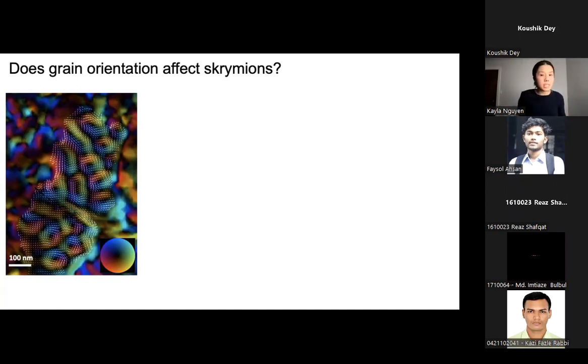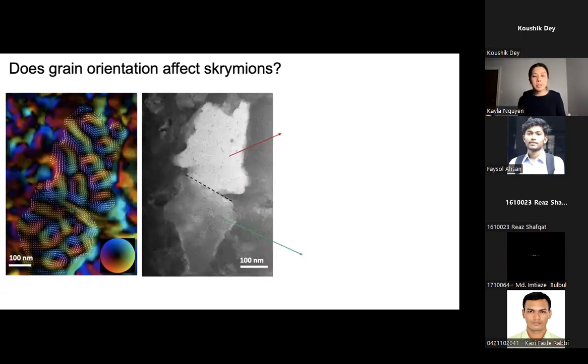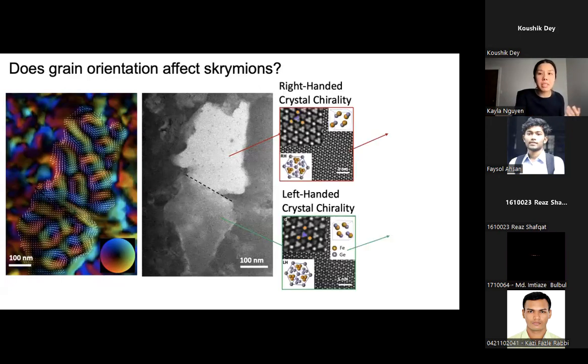So now what is going on with the sample? Why are we getting two different regions of different rotation of the skyrmion, even though we're applying the same field to the sample? So what we do is we go back to our traditional imaging of the grain structure, and we realize that these are two twin grain boundaries or domains. And then at atomic resolution, what we find is that the top grain has a right-handed crystal chirality, and the bottom grain has a left-handed crystal chirality.